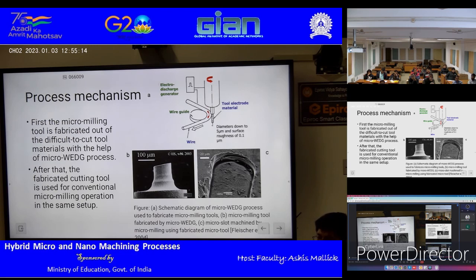So instead of that, if you have a wire EDG, it's very similar to wire EDM. What happens is there is a wire guide, and then you have that wire, and you can use that running wire from bottom to the top, right? The benefit of that is it has less contact surface, right? So it can really help you to achieve high aspect ratio microelectrode without any taper. And also the wear is running, so that means the wear of the wire cannot really influence that, right? So yeah, you can use the micro wire EDG, and you can bring down the diameter up to 5 micron, okay, which is very difficult to obtain using block micro EDM, but wire EDG can give you 5 micron